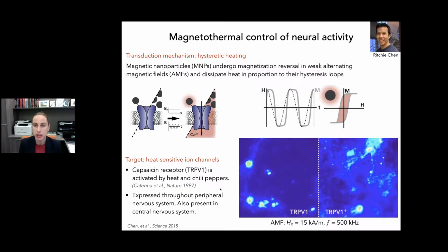So when we're talking about hysteresis, if we are considering magnetic nanoparticles that are about some tens of nanometers in diameter, we'll pick it such that it is a single domain magnet and it will have a magnetic moment. This magnetic moment can follow the direction of the magnetic field, but as we try to switch the direction of the magnetic field, the magnetic moment has to overcome magnetocrystalline anisotropy, and as a result there is a lag between magnetization and magnetic field. That lag manifests in the hysteresis loop, and the area of the hysteresis loop is proportional to the heat dissipated by the particle. And if we change the frequency, we can have more cycles of this heat dissipation.